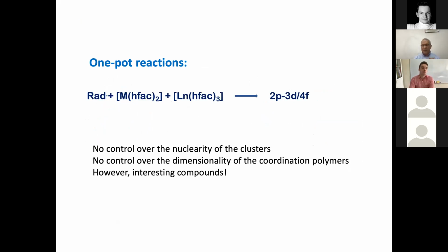spin carriers simultaneously. This is challenging from the synthetic point of view. It is not so easy to put together in one-pot reactions two different metal ions and a radical. So most of these syntheses reported in the literature, including ours, are rather serendipitous cases, because it is difficult to control the nuclearity of the resulting clusters or the dimensionality of the coordination polymers, or whether we can obtain discrete species or coordination polymers. Anyway, all these compounds are interesting and deserve to be investigated.